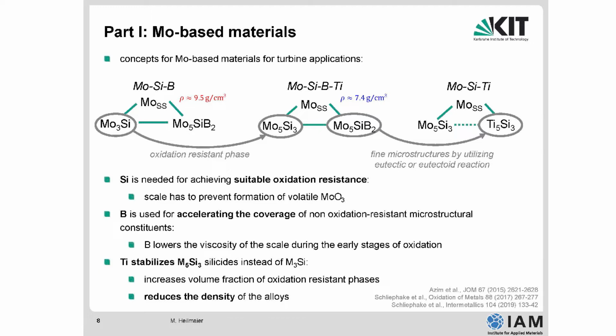For example, you could add boron. Boron is used for accelerating the coverage of the non-oxidation resistant microstructural constituents. Boron lowers the viscosity of the oxide scale which forms and thus provides rapid oxidation protection. But now there is a drawback here, again a small number. Rho, this is the density, the specific density of the alloy, mass divided by volume, is 9.5 grams per cubic centimeter. This is beyond the density of nickel-based alloys. Roughly speaking, nickel-based alloys have a density of 8 grams per cubic centimeter. So you need to do something to make the alloy lighter, not that heavy.